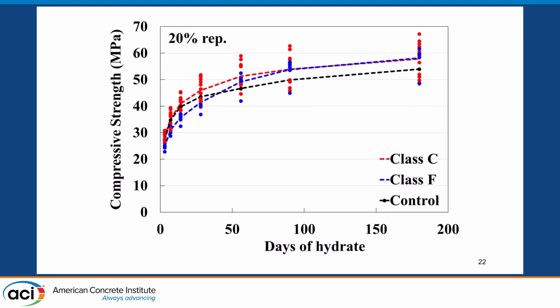Now, you might say, okay, cool, I see these are the averages here. You can see on average, Class C has an earlier strength than Class F, but longer term, they're about the same. But notice the spread. Notice how I have data points that are easily 10, 15% higher than the average, and I have some that are lower than the average. So just calling them Class C ash or Class F ash, although that's what we do today, maybe we can do better than that and better understand what's going on.